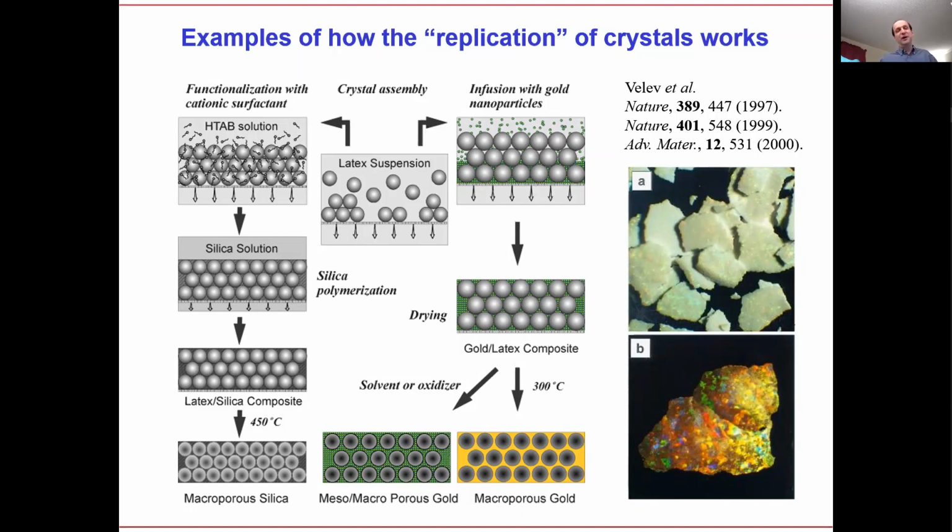So there were some folks, mostly physicists, who were trying to do it the direct way, which is you melt a metal and try to infuse a crystal out of silica, for example. Those of you who have taken my class know that this is not going to be easy, because of the very high capillary pressure that you need to apply in order to infuse the crystal with the metal.